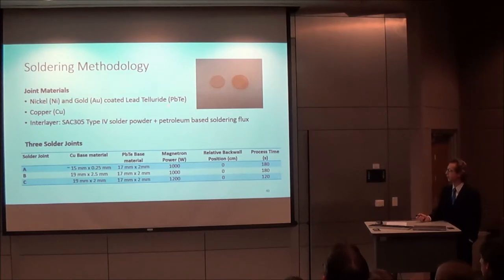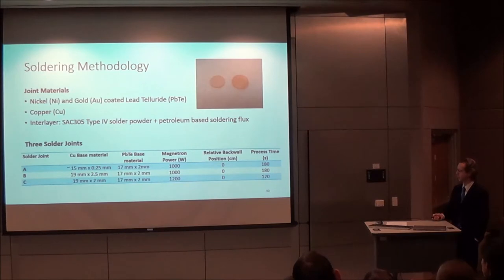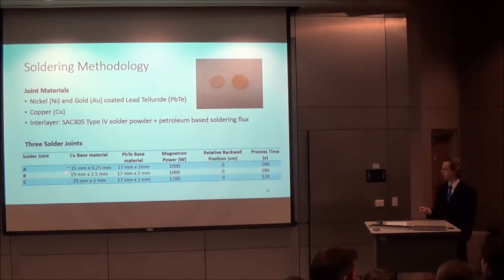The methodology used for the solder validation is as follows. The two base materials were copper and lead telluride. The lead telluride is a thermoelectric ceramic that is coated with a diffusion barrier of nickel and gold. The interlayer used was SAC305, the abbreviation for tin, silver, and copper: a 96.5% tin, 3% silver, 0.5% copper solder, with a type 4 morphology. Then also a petroleum-based soldering flux was used. Here are the parameters for the different joints: the sizes, the power used, the time, and the relative back wall position.